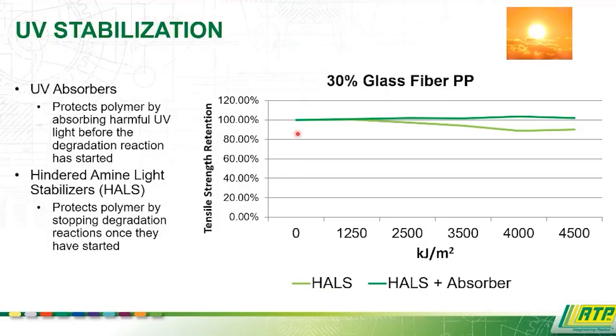See in this graph, 30% glass fiber polypropylene. When stabilized with HALs, we'll start to drop off a little once we get out into some extended accelerated weathering, while HALs and absorber will maintain those properties even further. I don't have a non-stabilized, but you'd see a steady drop once you get out here in those properties.